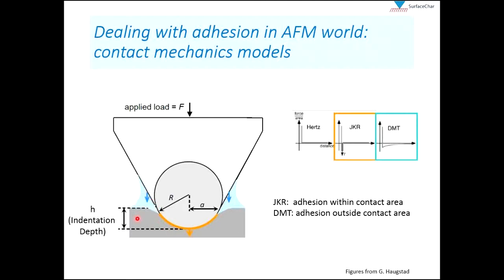The first one is called DMT, and that accounts for adhesion outside the contact area in the blue areas shown here. You can see a force versus distance curve. This is what a DMT would look like. And then for samples that have more adhesion or stickier, we have JKR, which accounts for adhesion within the contact area shown here. And these are, again, both models that incorporate adhesion, unlike the Hertz model, which is our basic contact mechanics model, which does not account for any adhesion.